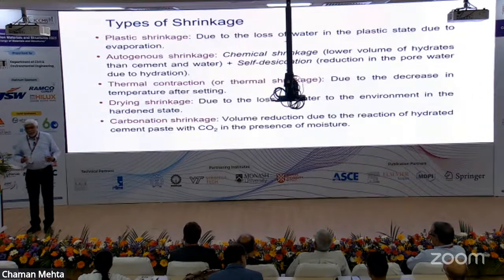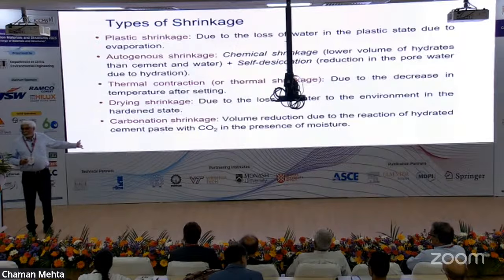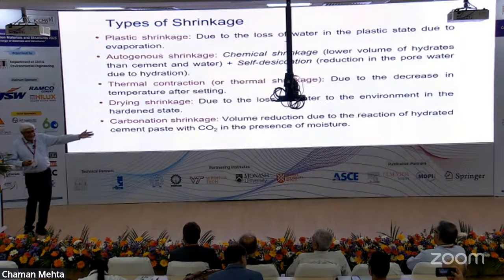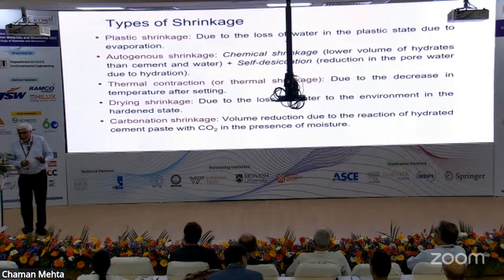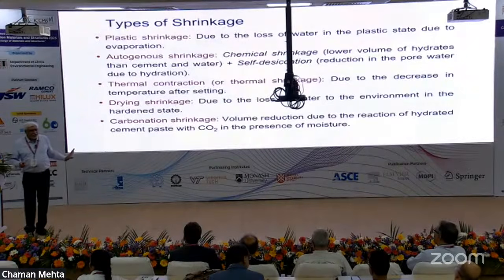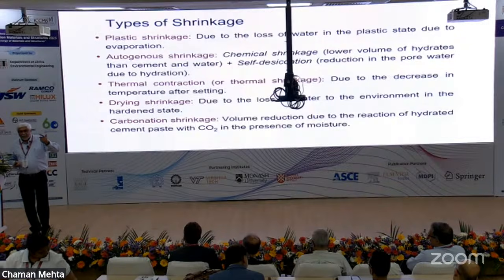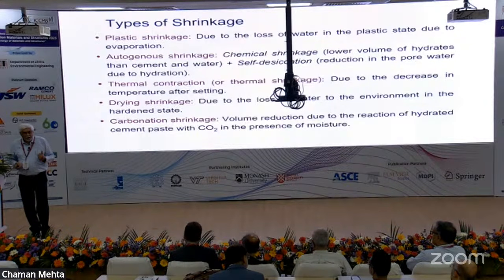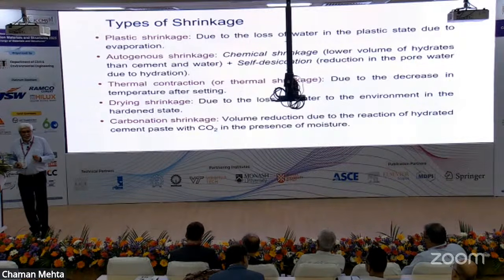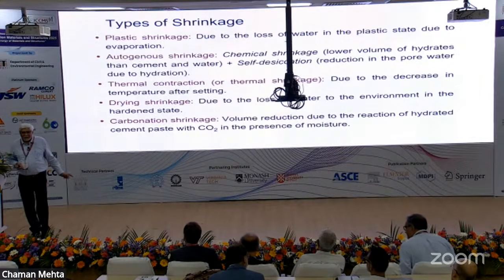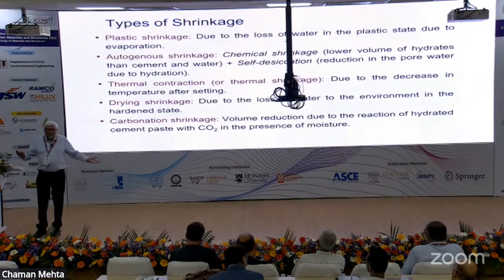Now, adding on to what Gianluca said about the 2 types of shrinkage, I'm going to give you 3 more, because we start a little bit earlier. Plastic shrinkage is very fresh concrete cracking. This in India is tremendous. We have huge problems. People will go for lunch and come back and the concrete is cracked. And who will they blame? The cement or the RMC? They forgot that they have to cure. When is curing usually done? After 24 hours. And if you cast concrete on Saturday, when do you cure? Monday. Concrete doesn't know this. Concrete doesn't know that Sunday is a holiday. It happily cracks.